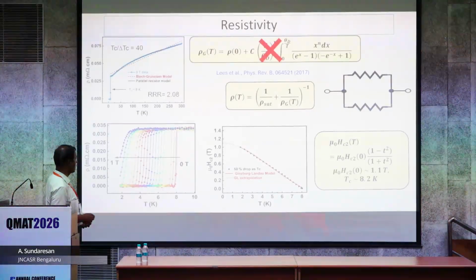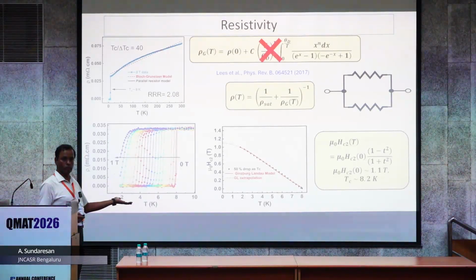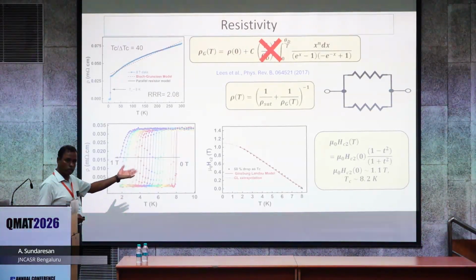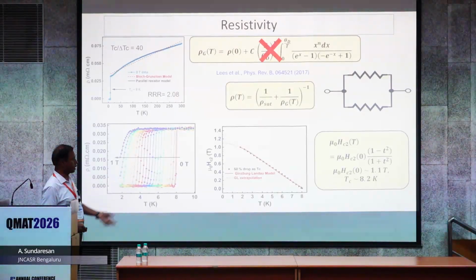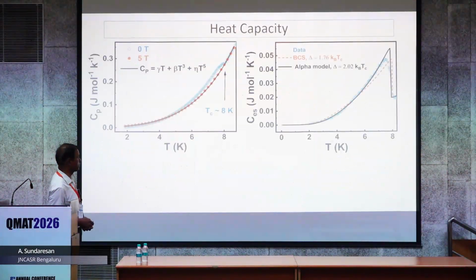We also estimated HC2 from the temperature dependent, field dependent resistivity using the 50% criterion, and we estimated HC2 which is about 1.1 Tesla. So you can suppress superconductivity with a small field, and look at the normal state properties.